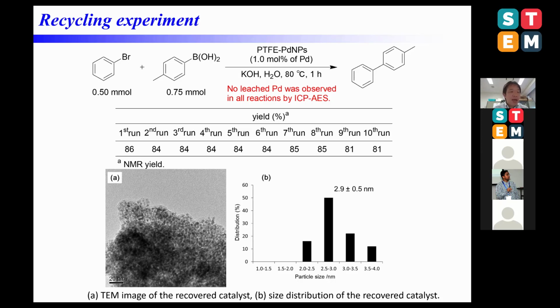Similarly, the size of the palladium nanoparticles was similar and no aggregates were observed by TEM after the recycling experiments. It's a very important point. This catalyst is very useful for this reaction.